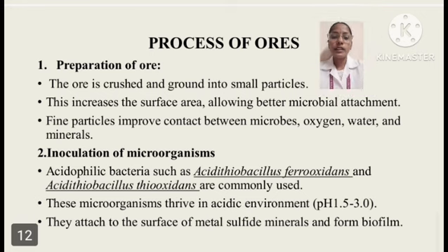The second process is inoculation of the microorganisms. Two microorganisms are mainly involved in the process: Thiobacillus ferrooxidans and Thiobacillus thiooxidans. The organisms thrive in an acidic environment. The pH is 1.5 to 3. They attach to the surface of the metal and sulfide minerals and form a biofilm.